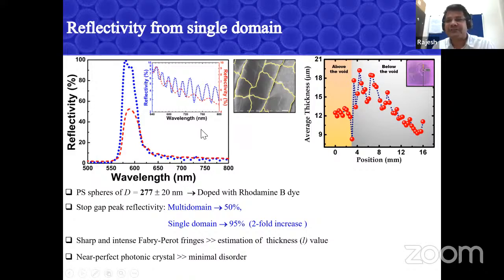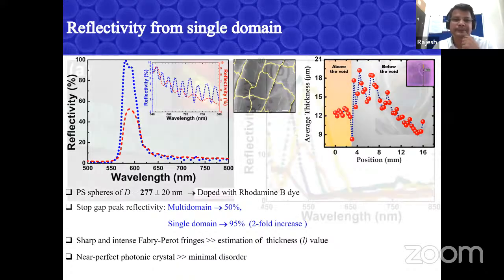And what is more interesting, we found that you can also get nice Fabry-Perot fringes, which I zoomed in on here. From there, you can find out the thickness of each of these domains. These interference fringes will give you the thickness value, because you know the refractive index value. So you can put in interference conditions and estimate the thickness. You can see that our sample actually has a huge variation in thickness. And this variation in thickness is really a game changer for these photonic crystal samples, which I will probably show you. I'm really running out of time.